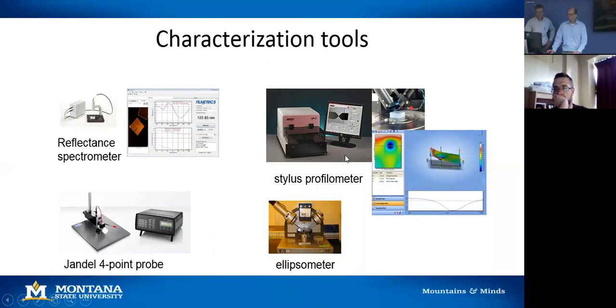We have a stylus profilometer where you can measure and scan primarily one direction very accurately. In the second direction, you can step over and get a map of the surface. This is good from 50 angstroms to hundreds of microns. Think of it as a very crude AFM, which can be sub-angstrom in resolution. This is 50 angstroms in resolution at its best. Then we have a 4-point probe for electrical conductivity of your films.